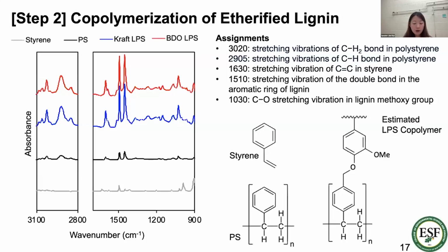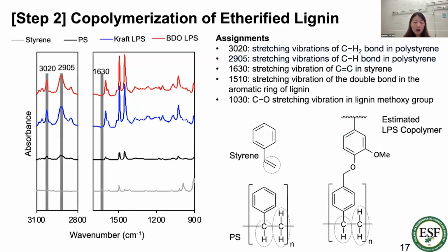we measured the FTIR, and styrene has the vinyl group in its structure. Once the copolymerization initiated, those vinyl groups disappear. So as we can see, at the wave number 1600 area, the vinyl group bending disappeared in the copolymerized structure. And also, once the polymerization started, some methylene group and methyl group peaks were generated once the copolymer was prepared. So we can see the additional peaks showed up in the polystyrene, Kraft LPS, and BDO LPS copolymer.